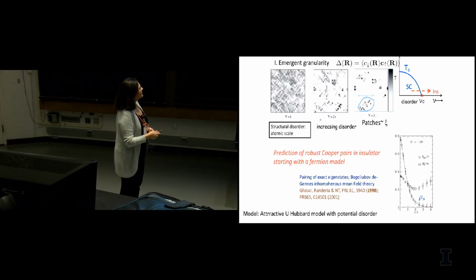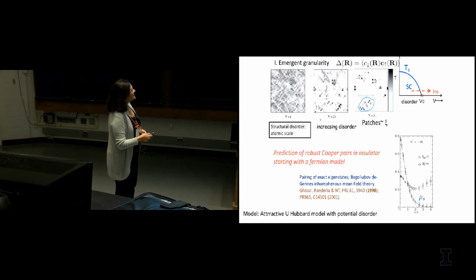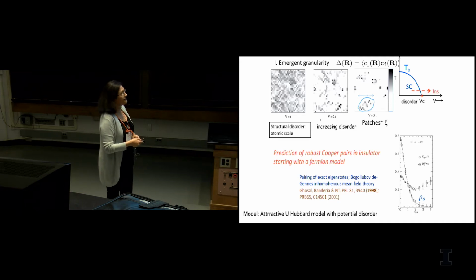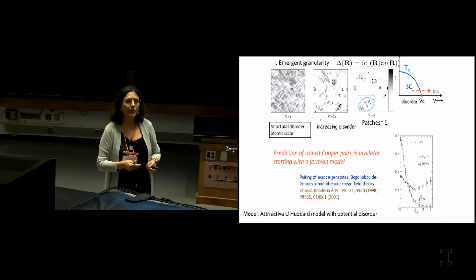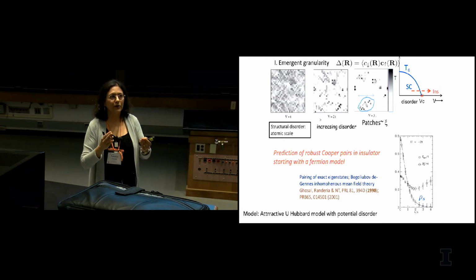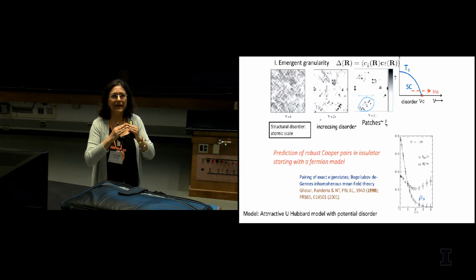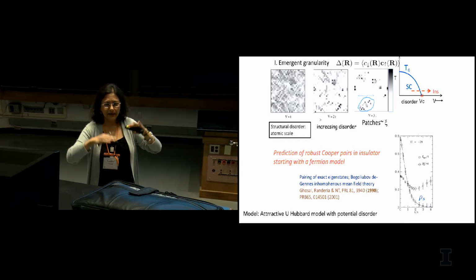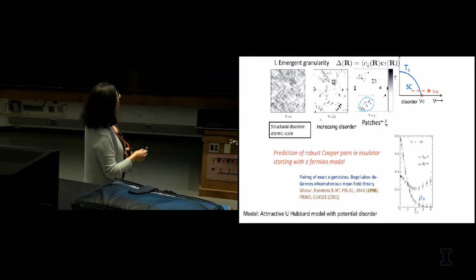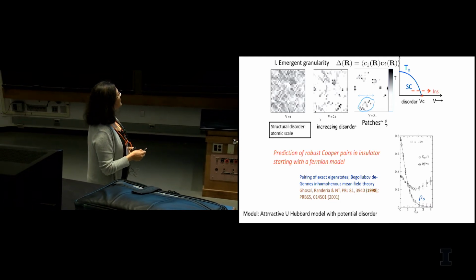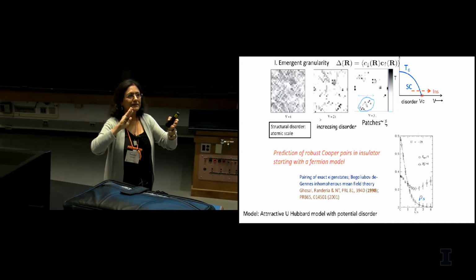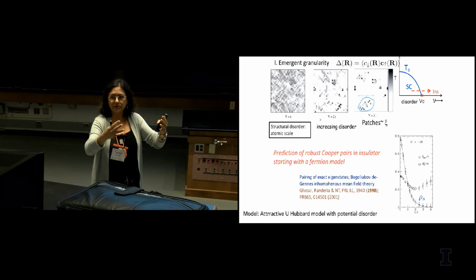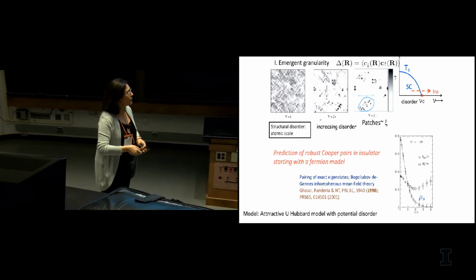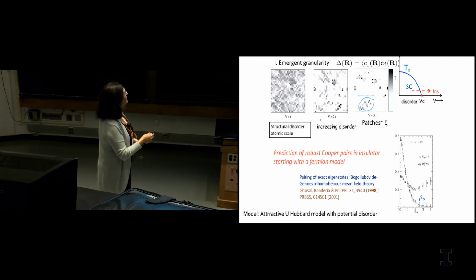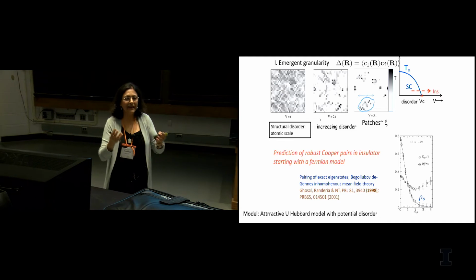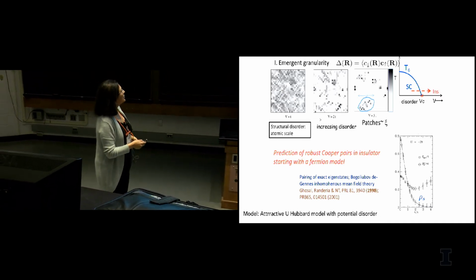You see the superfluid stiffness becoming extremely small, and this is even within mean field theory. You can see it becomes very small, and that connects with some of Tony's work where he derived bounds on the superfluid density in a system that has some inhomogeneity. And here we extended that to these disordered systems where you can show that when you try to put a twist on the system, the energy cost of that twist can actually be absorbed in these non-superconducting regions, thereby giving you a very small increase in the energy for a given twist, and hence a very small superfluid density.